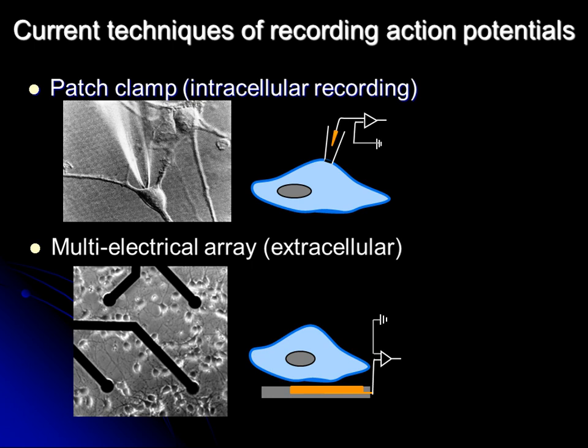For intracellular recording, a glass pipette manually approaches the cell membrane and breaks through it. The glass pipette is fitted with a measuring electrode. Therefore, we are measuring the membrane potential difference between the electrode, which is connected to the cytosol, versus a reference electrode, which is outside the cell in the solution. For extracellular recording, on the other hand, the cells are growing on top of the electrode. So we are measuring the potential difference between the measuring electrode, which is very close to the cell, versus the reference electrode, which is very far away from the cell.